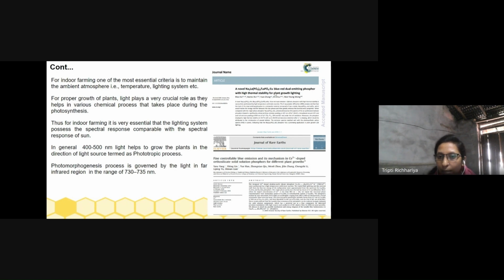On the basis of this, this article reports a sodium lanthanum phosphate material. It is a diphasic material, and due to the multi-site occupancy of the dopant ion and the coexistence of the Eu2+ and Eu3+ ions, this material acts as a dual emitting material. That means it produces red as well as blue region light. So this material is the most suitable for fabricating LEDs that are useful for plant growth inside the room, or in indoor farming.